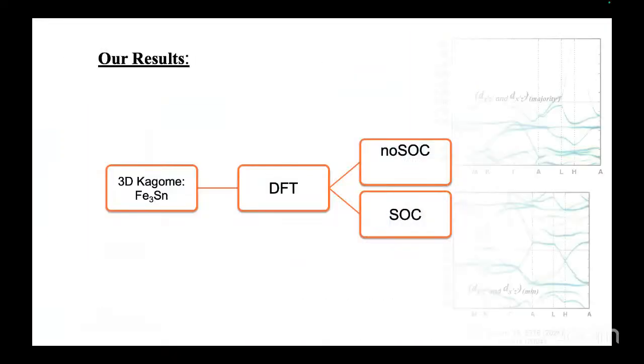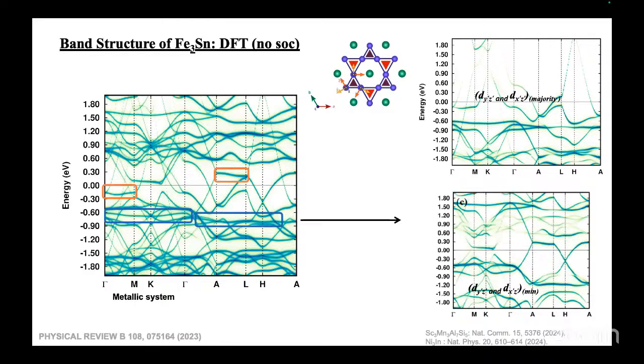These are the DFT results that I got for this system without spin-orbit coupling. In the band structure we can see the presence of nearly flat bands near the Fermi surface, which do not cover the complete Brillouin zone. They cover about half of the Brillouin zone around -0.6 eV, and on the other half we also see a nearly flat band, though not completely. That is quite expected, because this three-dimensional structure has a strong interlayer coupling, which does not allow the flat bands to be present throughout the Brillouin zone.